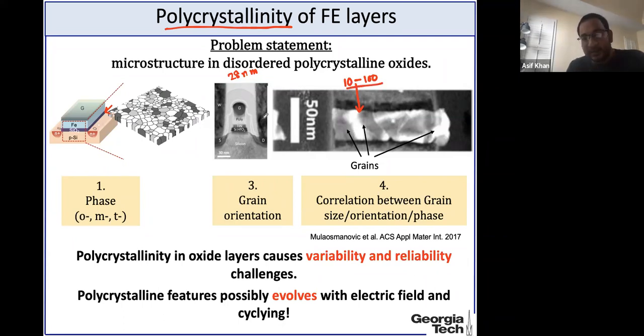Now, think of, for example, a 28 nanometer node with a channel length of probably 30 nanometers and width of 100 nanometers. And within it, we have 8 grains. Having 8 grains in one device is a big problem. The reason is that all these grains are different in terms of phase, size, orientation, as well as there might be correlation between them.